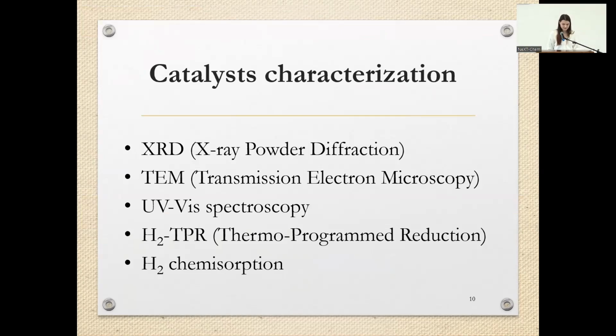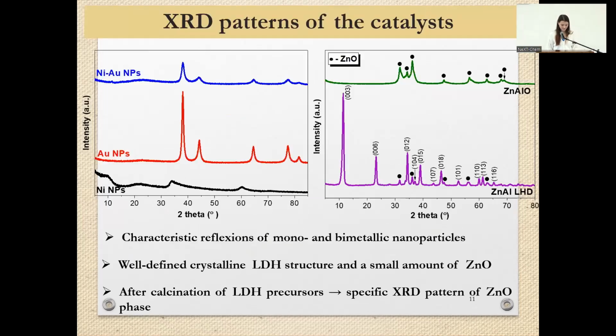We have characterized our catalyst using the following techniques: X-ray powder diffraction, transmission electron microscopy, UV-vis spectroscopy, temperature programmed reduction, and hydrogen chemisorption. Here you can see the XRD patterns of the catalysts. In the first spectra, we observe the characteristic reflections of mono and bimetallic nanoparticles. In the second spectra, the well-defined crystalline LDH structure and a small amount of zinc oxide. And after the calcination of the LDH precursors, we observe the specific XRD pattern for the zinc oxide phase.